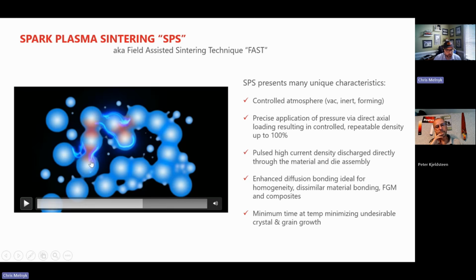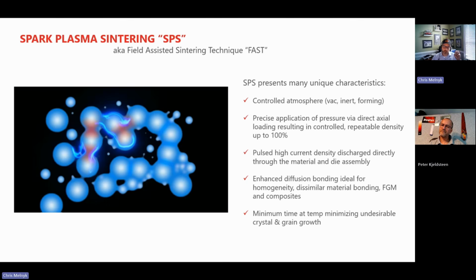Just resistive heating going through the material in most cases when it's metallic components or metallic powders that we're playing with. But also there's the field part. And so because we're pulsing, and that pulse conditions can change, and sometimes it's just direct, so it's not always pulsing. But in the cases of the pulsing especially, that change in current is what's going to generate the magnetic field, because whenever there's a change in electrical current, that's when you get that. And so every time you pulse one of these currents through, you give it a magnetic field in the area, which provides an additional effect to the sintering. So that's true even in the case of non-conductive materials. So there's still advantages to be had when we're sintering non-conductive materials as well.